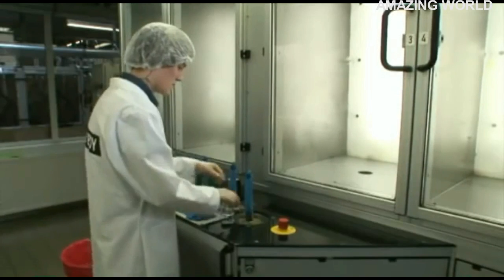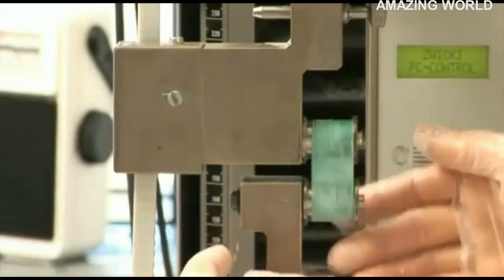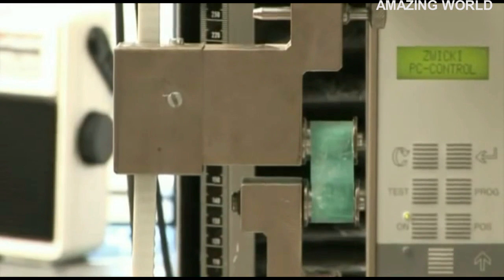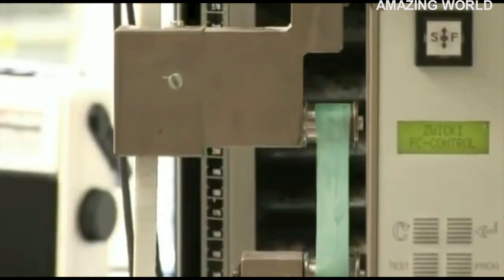To meet the consumer's high quality requirements, these sealed condom batches are now subjected to a whole series of elaborate inspections and tests. The international standard ISO 4074, for instance, requires that spot checks ensure that the bursting volume of a condom, after an artificial aging process and until the actual expiration date, must amount to at least 18 litres. All MAPA quality condoms exceed this threshold by far. The second test examines the condom's stretch resistance, where stretch coefficients of 700% or more of the original coefficient must be reached.